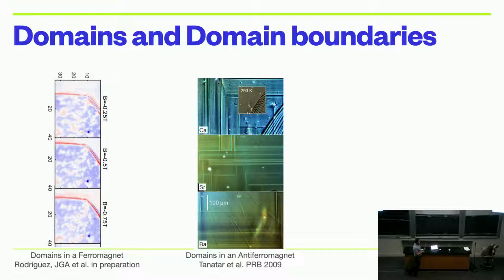Other kinds of phase boundaries are the ones that we were discussing earlier with the nematic susceptibility and the antiferromagnets. So here are three materials where these lines are different domain boundaries, where the nematic order is pointing in two different directions. Just as the spin is pointing in two different directions in the red and blue, here the boundaries are where the nematic orientation goes from left to right to up and down.